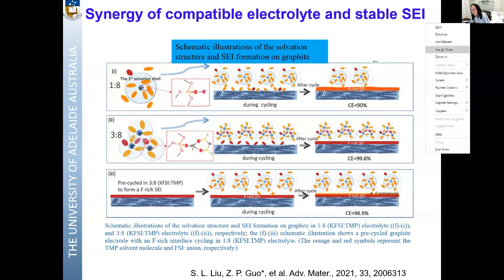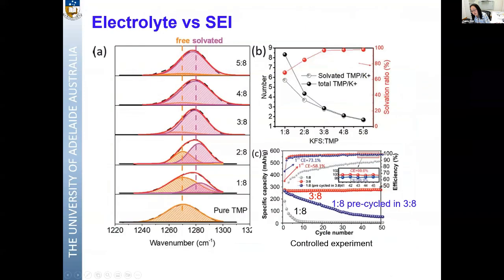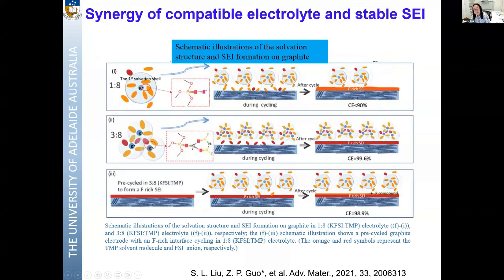So therefore, we can see here, if we pre-cycle the electrode in the high concentration electrolyte to form the fluoride-rich SEI, but later on we cycle in the low concentration electrolyte, still the capacity drops very significantly. So basically, the concentration is quite important to maintain long cyclability in this case. So this is our work on the development of non-flammable electrolyte for potassium-ion battery.